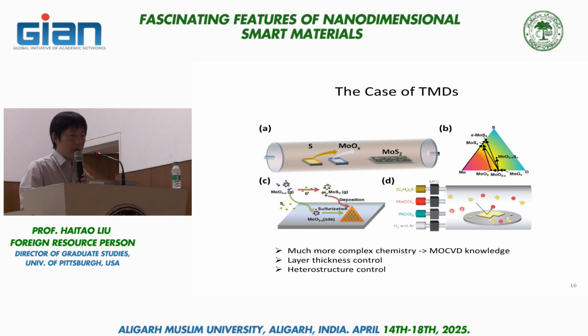The substrate used in a lot of those growths is also copper. Again, this is an adsorption and growth mechanism. The bulk solubility of most of those TMDs is pretty low in the case of bulk copper substrate. But people have used other substrates, even as simple as silicon wafer, in growing those materials.